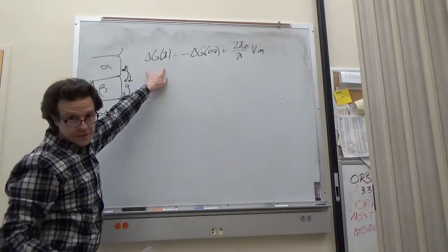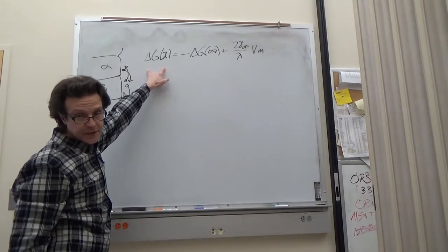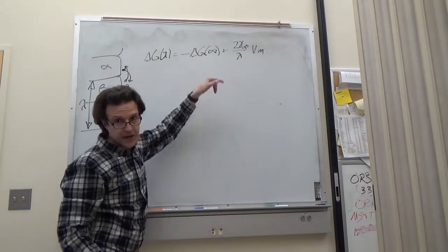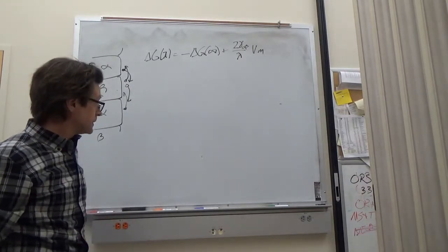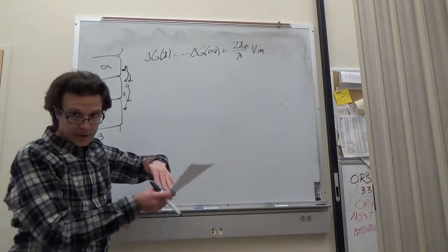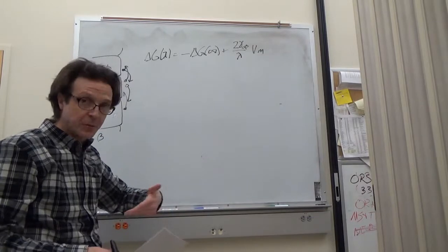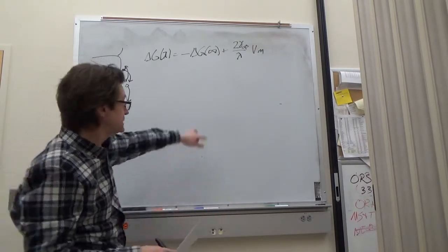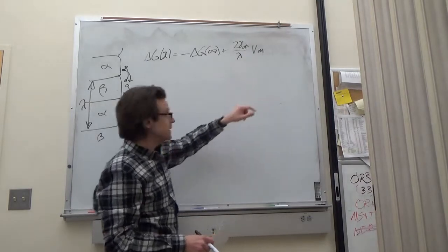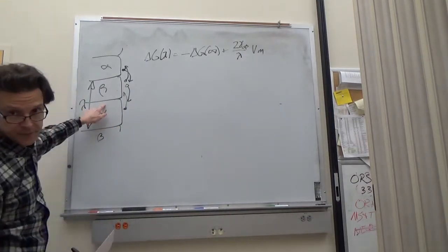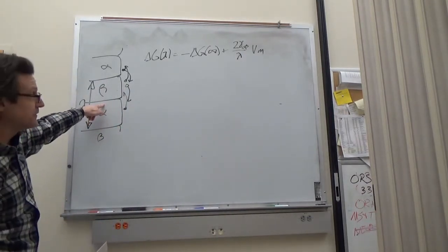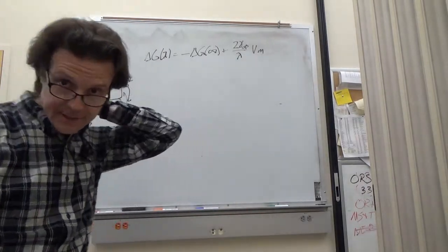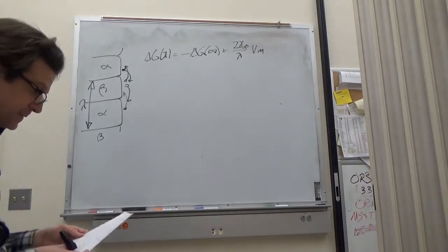And we've got the difference in the free energy driving the solidification is a function of the difference in the free energy for an infinite separation. So this is just a system where you're creating alpha and beta, but there's no interfaces. And then we have this interface energy, which comes about from the fact we have an interface, and the spacing tells us the volumetric density of the interfaces.